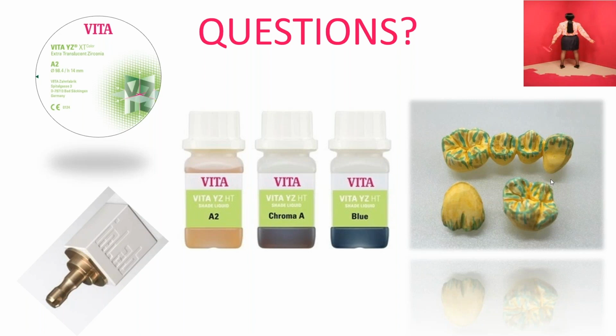We have one question, and it goes back to why glaze at a low temperature. Well, we glaze at a lower temperature twofold. One is that we don't want to disrupt the surface, if you will, of zirconia. Because of those large grain sizes, we do a lower temperature because it flashes a little bit thinner, and it makes sure that it absorbs in, if you will, in between these microscopic grain boundaries. And then the other thing, of course, is that with zirconia, if you have a pre-shaded or you're using the colorant, if you burn out too many times at a high level, the oxide pigments will actually start burning out as well.